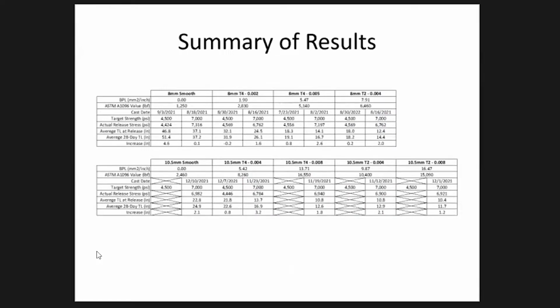Some of the results, I know you can't read this table, but I want to point out one of the interesting things about these wires. This was the 8mm smooth wire, and we had a transfer length of 37 inches on the 8mm smooth. When we went to the 10mm smooth, we have a lot more force on the wire, but the transfer length was only about 23 inches. So why is that? When we have a smooth wire, that wire is dependent on the surface characteristics, any residual lubricants, any rusting. So when we have a real smooth wire, the transfer length is governed by that. As soon as we add indents, then things work much better from a correlation standpoint.